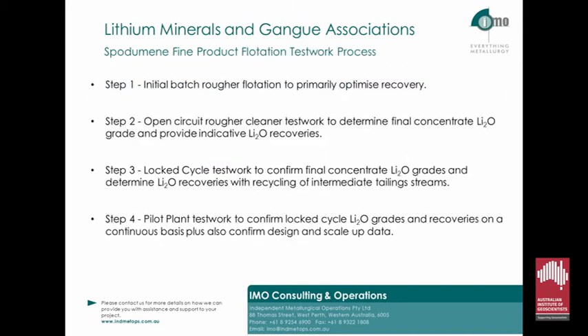The downstream process isn't any less complicated and ultimately also requires confirmation from piloting, especially as the middlings fraction generated from the heavy media circuit isn't generally available until the DFS. This means that upfront testing conducted on commonly the minus 0.5mm fraction generated from whole ore material needs to be confirmed on a combined heavy media separation middlings and less than 0.5mm products.